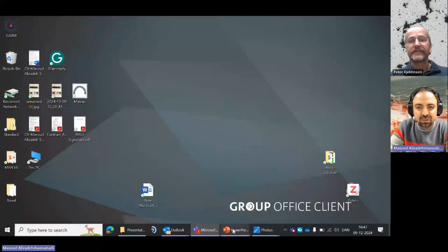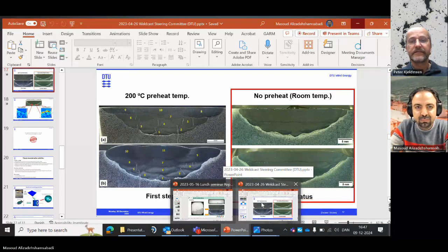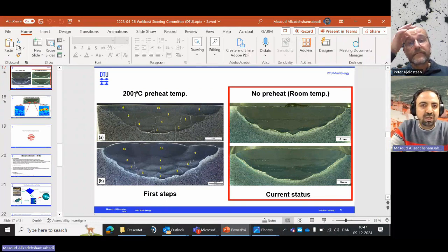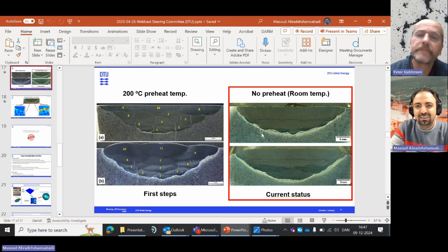Okay, let me share my screen. As you can see, I showed in the first episode that this is the first step in the Weldcast project, where we used a 200-degree preheating temperature, and there are a lot of cracks everywhere. And this is close to the final result. There are some really minor cracks here, but we use no preheating, and the welding starts at room temperature.